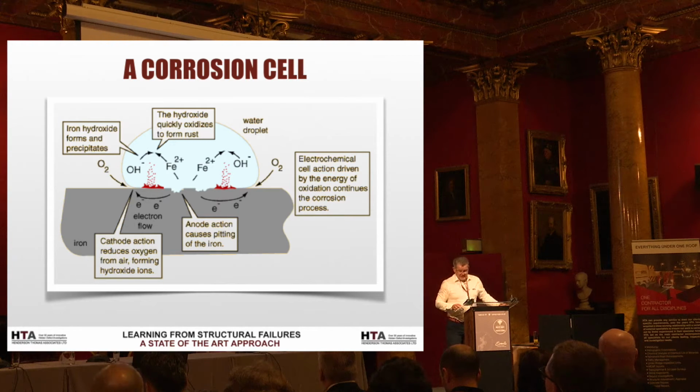Generally what you'll see is on bridges or buildings, and we did a lot of work back in the 90s when I was at Taywood Engineering, where we were looking at an elevated police station in Blackpool. They had major problems, they had poor construction details, so the bars didn't have a great deal of concrete cover. We got very high half cell readings, which I'll come onto in a minute, which indicate corrosion. We can actually see that. Because it was an elevated structure very near the sea, we had very high levels of chloride in the concrete, all adding up to a lot of problems with corrosion.